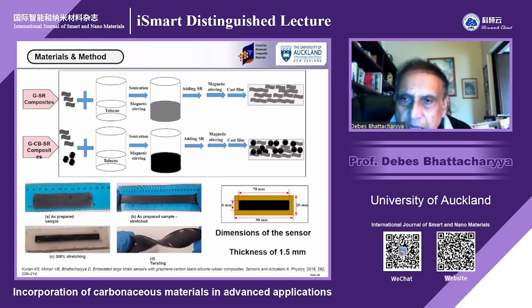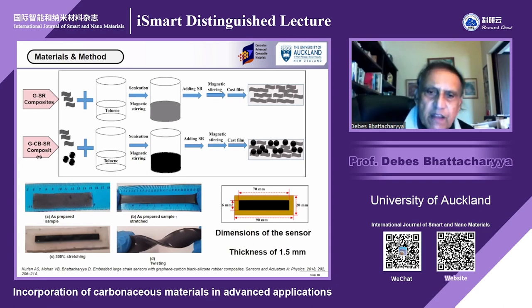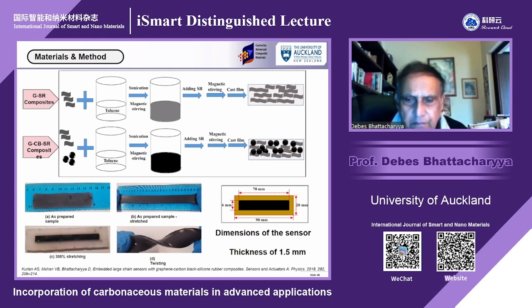Then they allow some kind of contact between those platelets, and if there is any flow, it will be helped by those little carbon black particles. They are not as big as the platelets. They are helping that. By doing that, we also created a very flexible sensor. Even with 300% stretching, it worked very well. It stretched, and you can also twist it. And there was a publication of that.